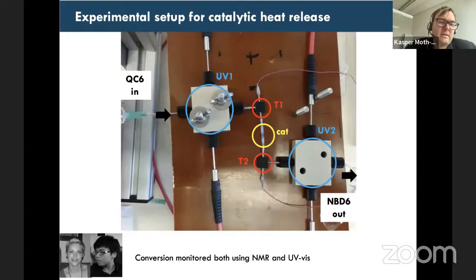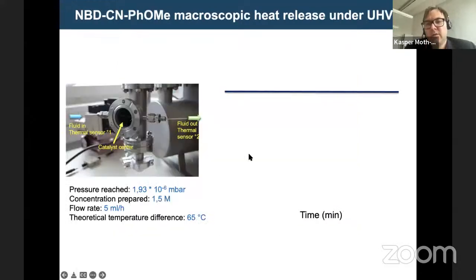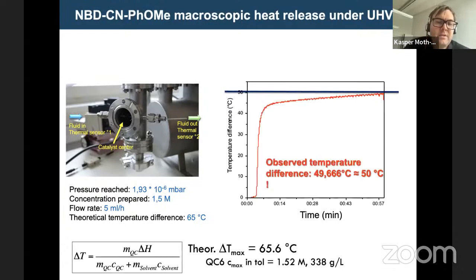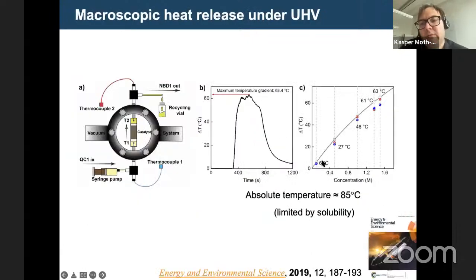Quite fast, we found out that there's a lot of energy losses. If you have a small device and it's out in air, then you're losing much of your heat to the surroundings. So next generation device was put inside a vacuum chamber. And with that, we could finally see temperature increase when the molecule hit the catalyst. The temperature increased 50 degrees. And by fine-tuning this and playing with the concentrations, we could get up to 64 degrees temperature gradient, which is the current world record for such systems.